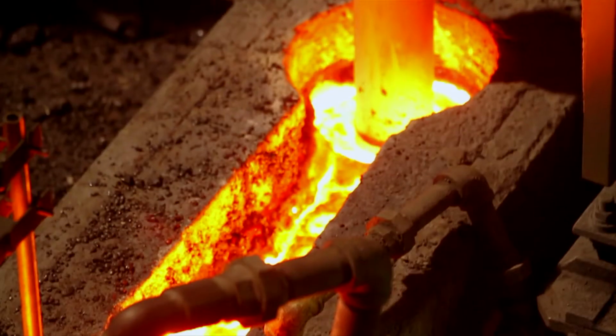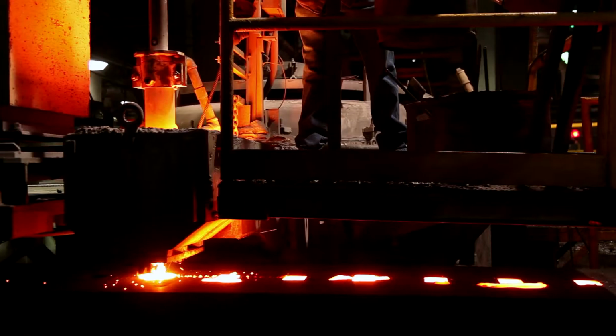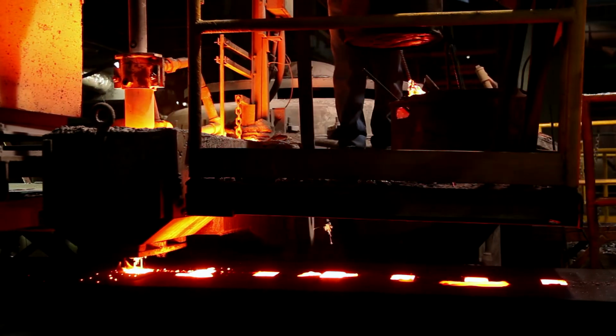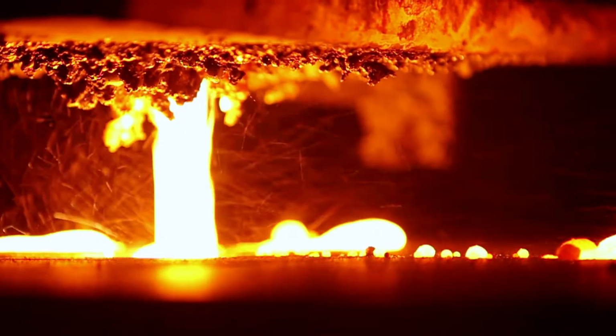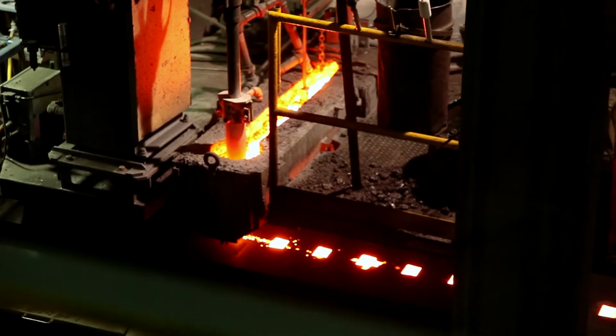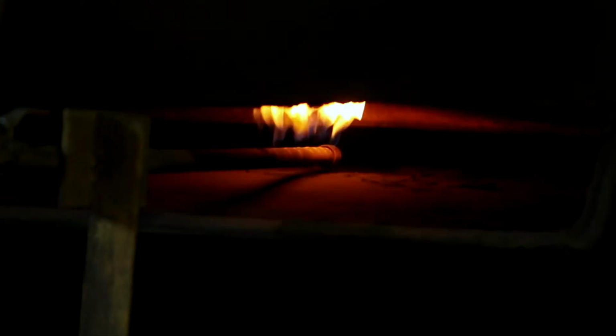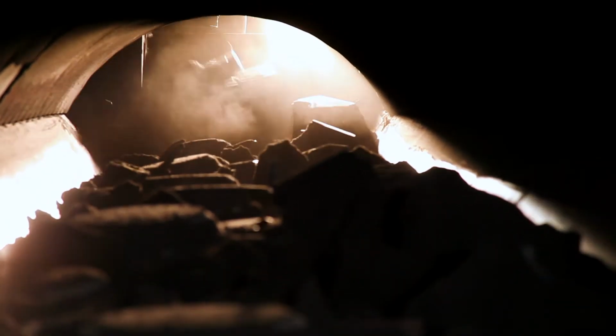In pouring our molds, the liquid metal must be between 2,480 and 2,520 degrees. This temperature produces the best finish for the castings. The cookware moves along a vibrating conveyor belt for about 40 minutes to shake off the molding sand. The sand is captured, cooled, and recycled.